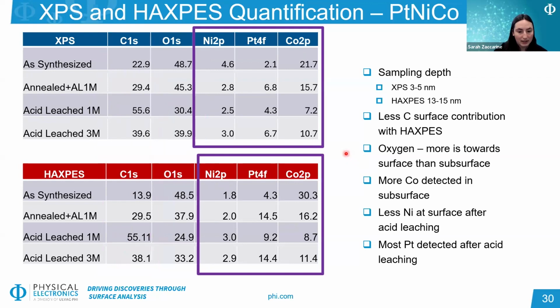And if we compare these three different metals, we generally see more cobalt detected with the chromium deeper into the sample than we do with the aluminum XPS source. We also see some changes in the cobalt that's detected. We have more cobalt present with both sources with the synthesized sample, and then once they are treated, we see slightly less cobalt. We also see differences in the platinum and nickel amounts.